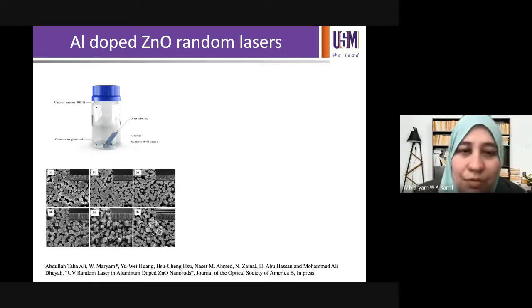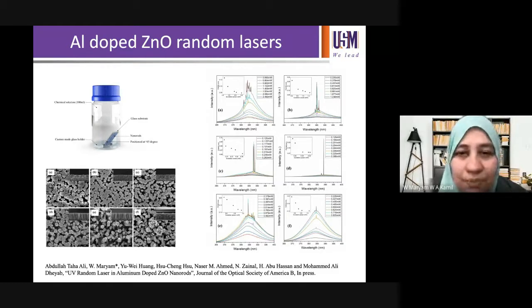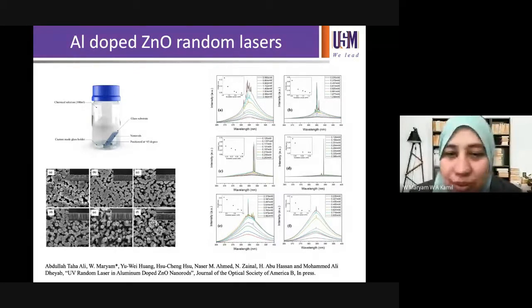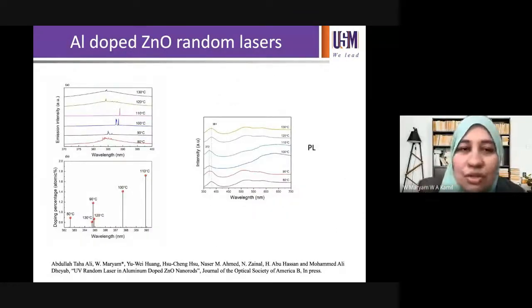From that, we did the lasing measurements and noticed that some lasing is very superior compared to the rest, depending on the doping. When we wrote the paper, the reviewers were happy that this is due to the doping itself, so we don't have much counterback regarding the morphology. What we did see, however, is not just lasing that's more superior, but also that the spontaneous emission is very much suppressed. Not only that, we saw a change in wavelength.